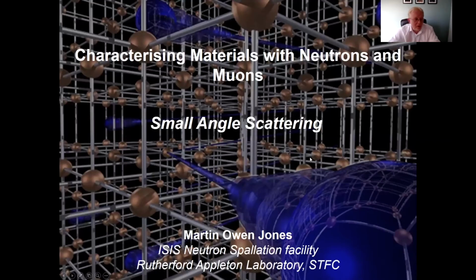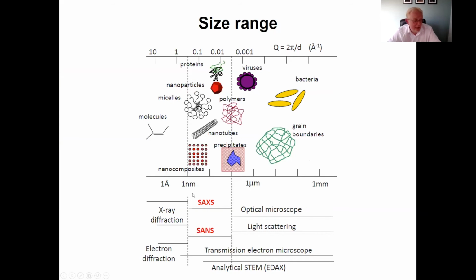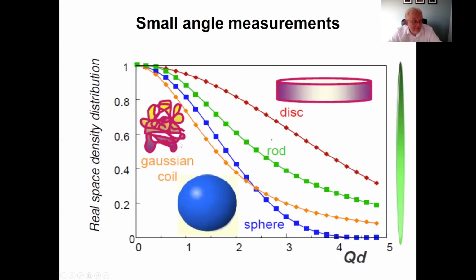We also do small angle scattering. Small angle scattering sits pretty much in between diffraction studies and microscopy studies, and it'll give you information about these agglomerates, about these complex materials, whether they be proteins or complex nanoparticles or micelles, polymers, nanotubes. Essentially the information from that, from the real space density distribution of your material, influences the shape of its response to the energy of the neutron.